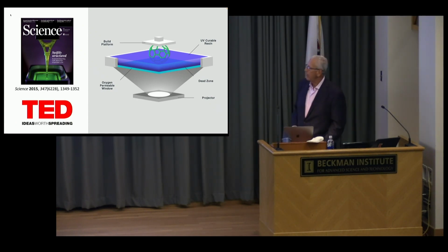So our approach for thinking about this was a variant of a DLP process where we're using light in 2 dimensions from a DLP projection system at 385 nanometers. We're projecting light through a window that's at the bottom of a reservoir for at least a partially UV curable resin. It will lower a platform into this resin, get very close to this window, and then we'll start to irradiate 2-dimensional patterns. And the part will adhesively bond to this platform, but not to the window, because the window is not only optically transparent, but it's permeable to oxygen. Oxygen inhibits the photochemistry that the light is triggering, and it never bonds to the window. There's always a liquid layer.